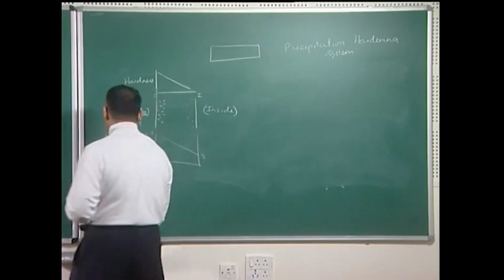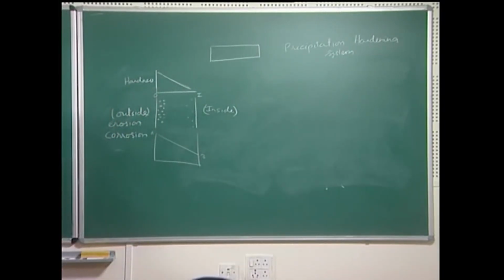In the case of a precipitation hardening system, the classic example is the aluminum 4% copper alloy system, in which we take the system to high temperature where you have a uniform solid solution. We quench the system to room temperature, typically from a temperature like 550 degrees Celsius, which according to the phase diagram gives you a uniform solid solution of copper and aluminum. When we quench it, at room temperature we have a supersaturated solid solution of copper and aluminum. Additionally, the system will also be supersaturated with respect to vacancies.